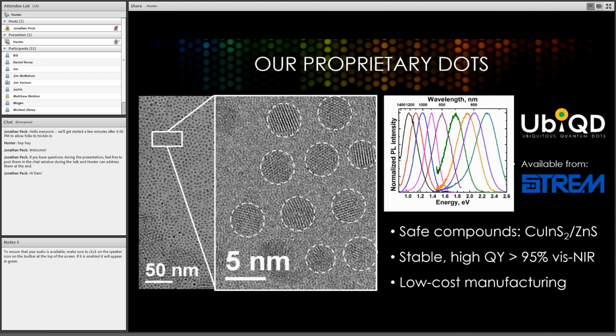Just a little bit more specifically on our quantum dots, they're also exciting because we're able to access a wide range of colors, not just the visible, but deep into the near IR, which is pretty useful for this application because we want to make a color-neutral window tint and dial in the luminescence to hit the band edge of silicon or perhaps other kinds of solar cells, but we mostly use silicon. We can also make materials with really high quantum yield. That means for every photon that gets absorbed, up to nearly 100% of those get converted into a photon emitted. And that's true not just for the visible, but also the near IR. And then we have a scalable, low-cost manufacturing approach.